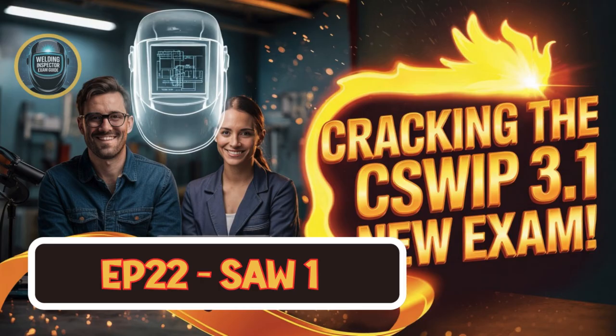Too high, and that wide, flat bead can become prone to solidification cracking, especially down the center line. Slag removal can also become much harder, particularly in narrow grooves. You might get a concave fillet weld shape, which isn't ideal structurally, and you risk over-alloying the weld metal from the flux, changing its properties perhaps undesirably. And if the voltage is too low? Too low gives you a stiffer, shorter arc. This can actually improve penetration in really deep, narrow joints and help fight arc blow. But go excessively low, and you end up with a tall, narrow, ropey-looking bead. And again, slag removal can be a real pain. Like current, changing voltage shows clear differences. A weld at 25 volts looks very different from one at 45 volts.